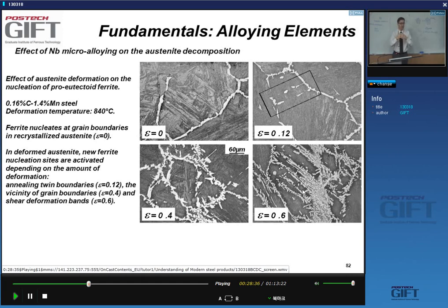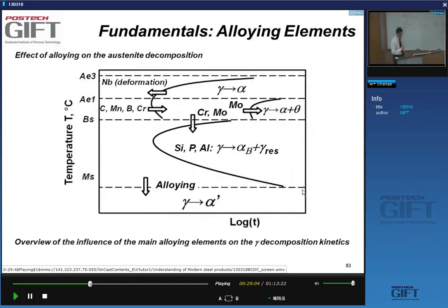and it should not transform. Deform it, and it shouldn't recrystallize. And you should be able to deform more and more without recrystallization, right? That's essential. And I told you it takes you less than 1 second to recrystallize material, so accumulating deformation is very difficult unless you add niobium. That is the importance of the niobium.